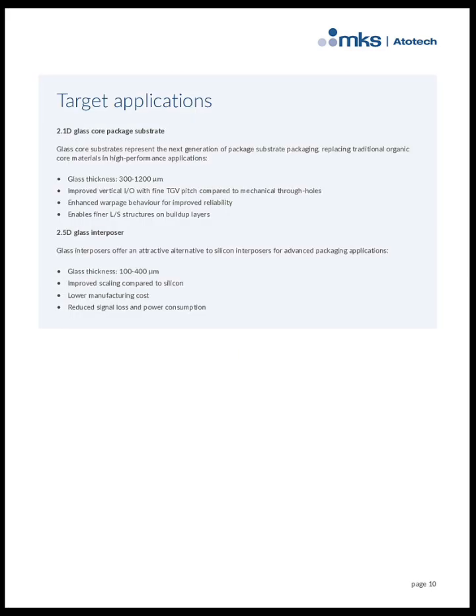Glass substrates target key applications in advanced packaging. The 2.1D glass core package substrate replaces organic cores in high-performance packages, offering thicknesses from 300 to 1200 microns, improved vertical I/O with fine pitch through glass vias, and enhanced warpage behavior for reliability. Meanwhile, 2.5D glass interposers serve as cost-effective alternatives to silicon, with thicknesses between 100 and 400 microns, better scaling, lower manufacturing costs, and reduced signal loss and power consumption. These applications highlight glass's growing role in next-generation electronics.